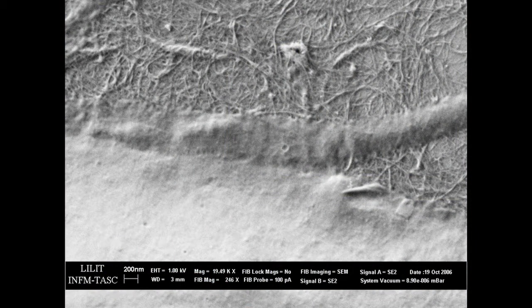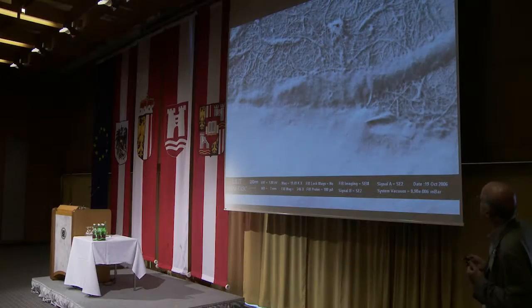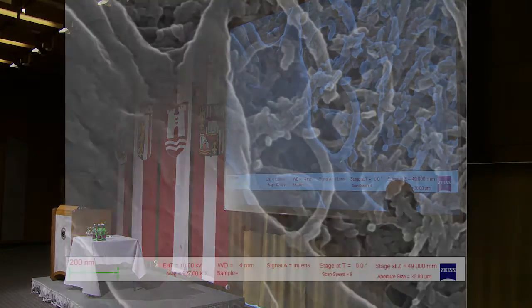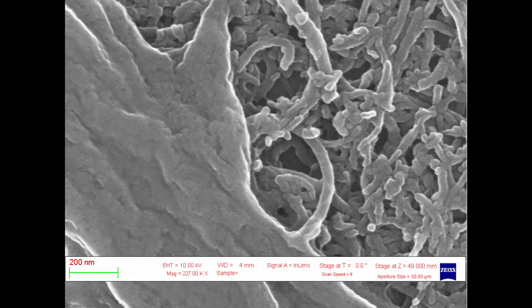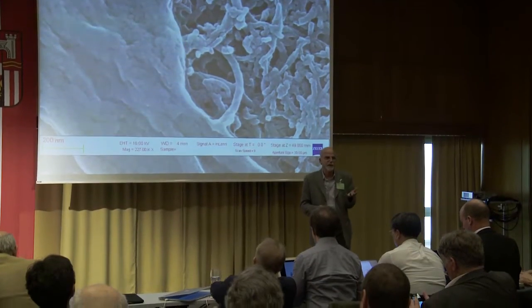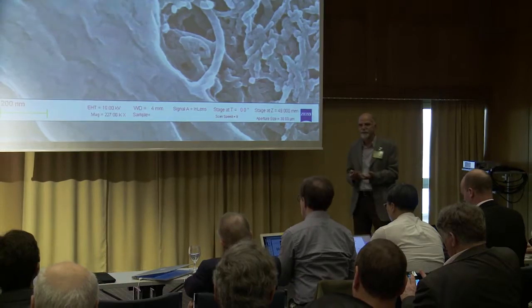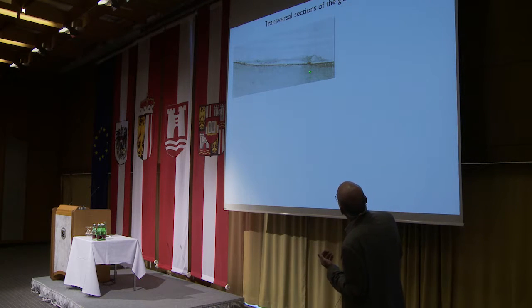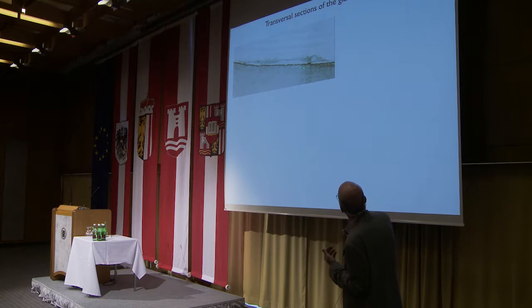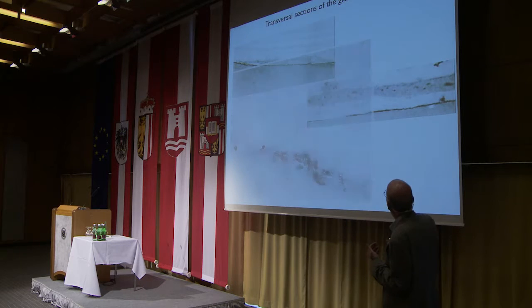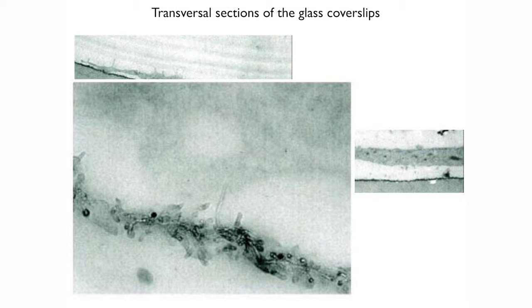But what is outstanding here is that the interaction of the nerves with carbon nanotubes is really, really impressive. We can see that nanotubes really become part of the neurons. As you can see here also in another experiment, nanotubes can penetrate inside the cell. So basically what we believe is that there is a tight contact between neurons and carbon nanotubes, which makes the two entities behave as a single whole. And if we look at other perspectives, for instance, if we cut the glass cover slips into transversal sections, so now this is the glass, this is the layer of carbon nanotubes, and this is a section of the neuron, we can see that normally the neuron floats on the layer of carbon nanotubes.